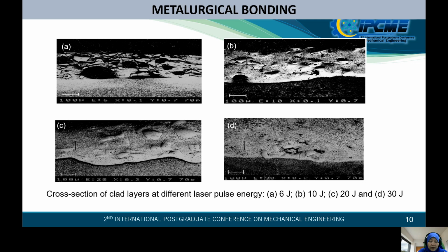Figure show cross-section of clad layer at different laser pulse energy. A 6 joule, B 10 joule, C 20 joule, and D 30 joule. At laser pulse energy 6 joule, laser clad layer was discontinuous with large pores. While for laser pulse energy at 10 and 20 joule, the layer much more dense. And last, at higher pulse energy at 30 joule, complete melting and elimination of shrinkage porosity, produce good metallurgical bonding.